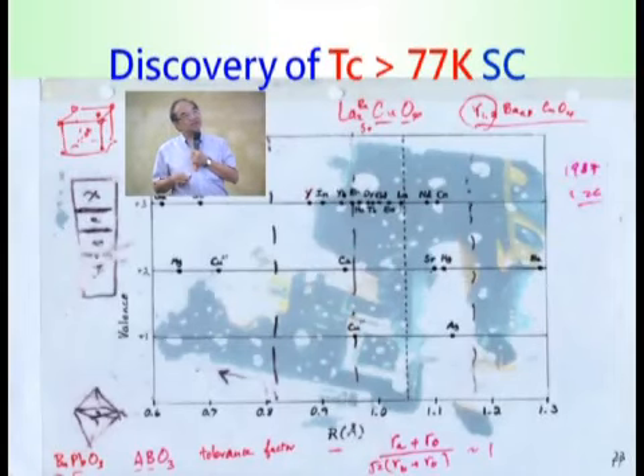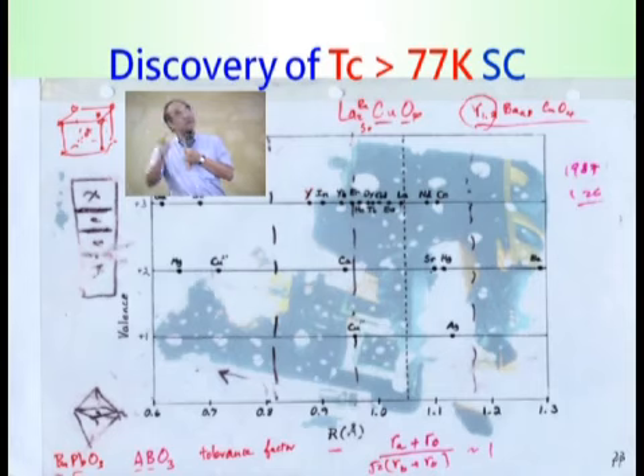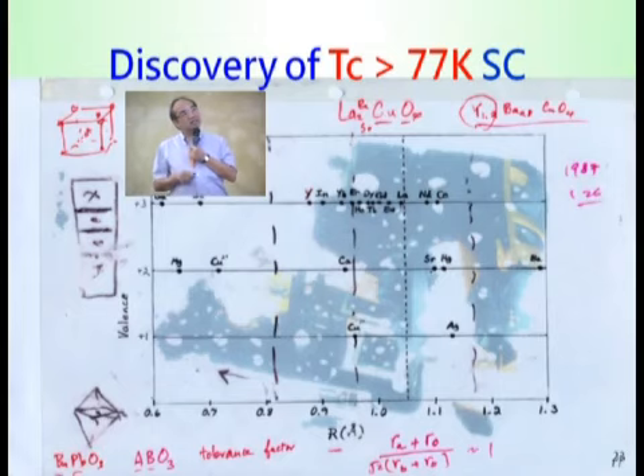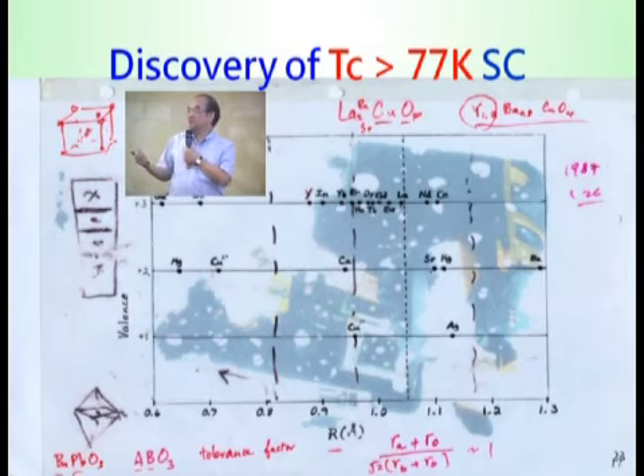And we plot a figure and then they make an assumption to be properly right. So we need to find something that, with the size of the ion we place, keeps the copper but changes the yttrium barium, and we use that as a mixed size. And we said, well, this line should be very ideal if we can find something that will go to that line. Okay. So this is a very simple geometry argument, not much of chemistry or really physics.